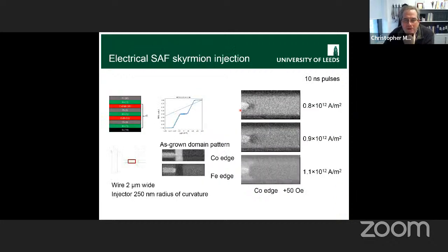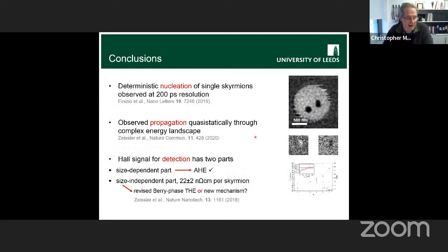And you can even sometimes nucleate a single skyrmion. There's a couple of examples here of a little patch of dark contrast. So these are synthetic antiferromagnetic skyrmions that we've nucleated electrically. So you can do a lot in these multilayers, and you can do it all at room temperature.